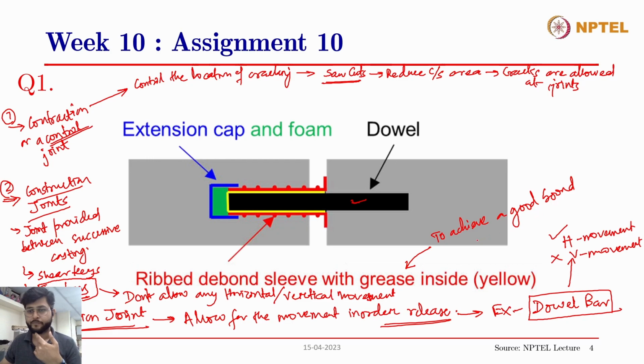because ultimately, even if we want the concrete to move across, like due to expansion, the concrete can come closer, or due to contraction, the concrete can move further apart. But we want the dowel bar to be in that place, and therefore, for that purpose, we want the ribbed debond sleeve, which will act as a sleeve for the dowel bar, that has to be intact. So we want a good bond between the sleeve and the concrete, but we want a grease between the dowel bar and the sleeve. So this grease, the yellow portion, is the grease,